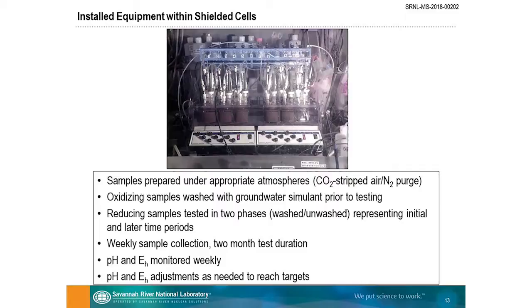Oxidizing samples were washed. Reducing samples were tested either washed or unwashed. Remember, the reducing was the beginning part of the aging process that we were interested in, so we looked at both. Collected samples weekly and continued for about 2 months. So we collected 8 to 10 samples to confirm we had reached an equilibrium and that we believe we had concentrations that were representative of the solubility limits for the radionuclides. We monitored the pH and the EH weekly, really continually, and we had to make adjustments in many cases to maintain those targets, or at least approach those targets.